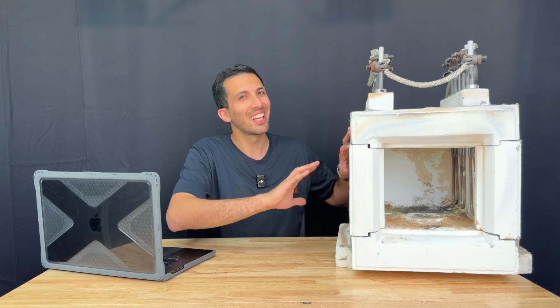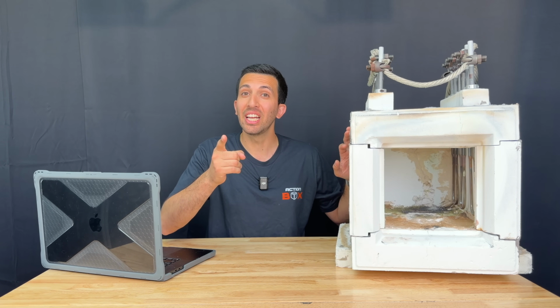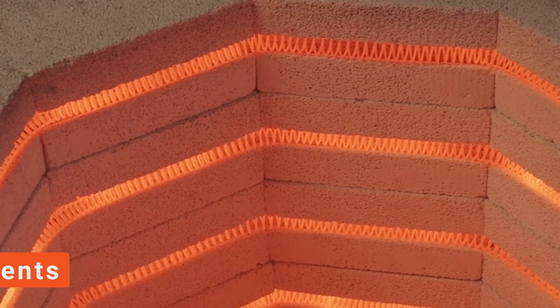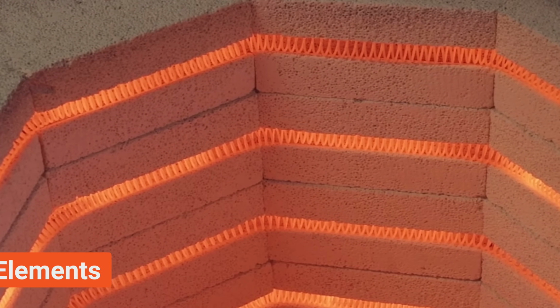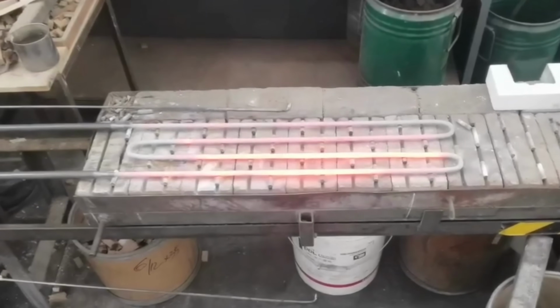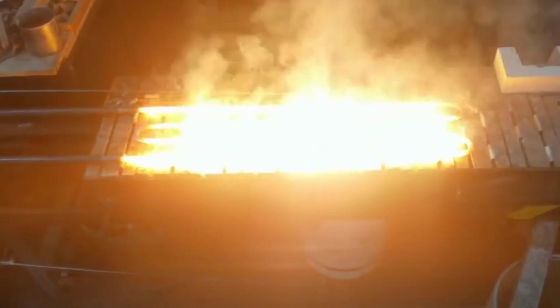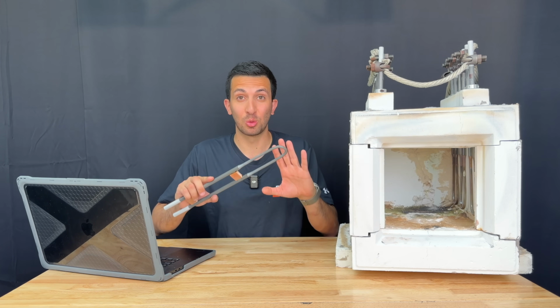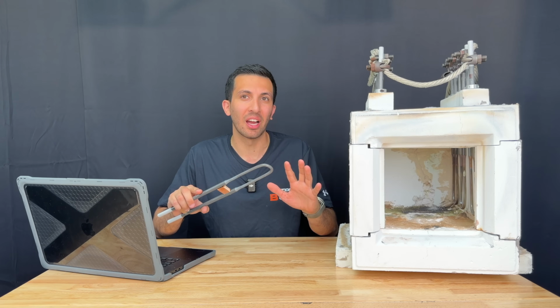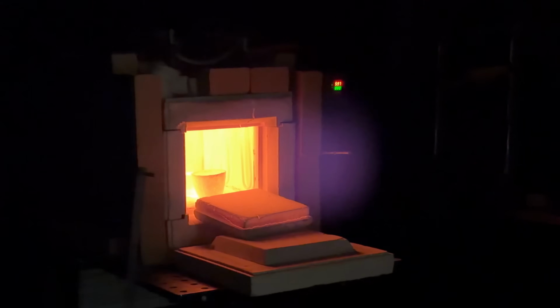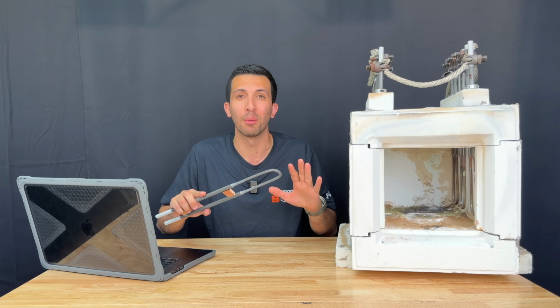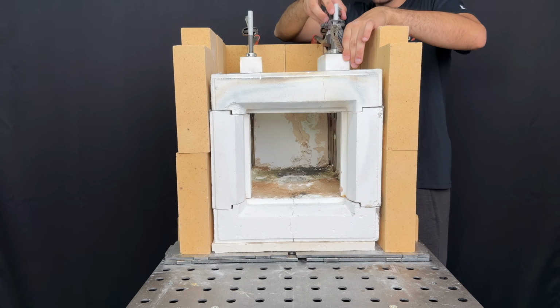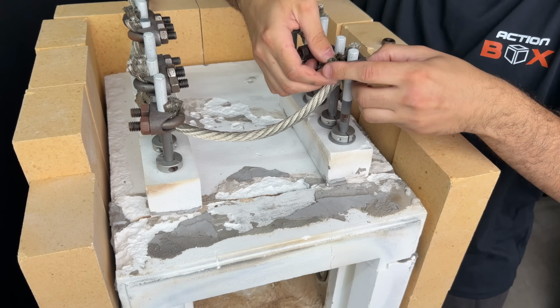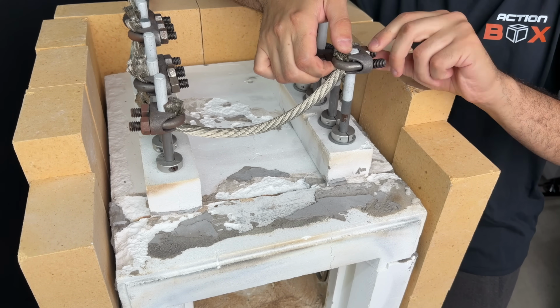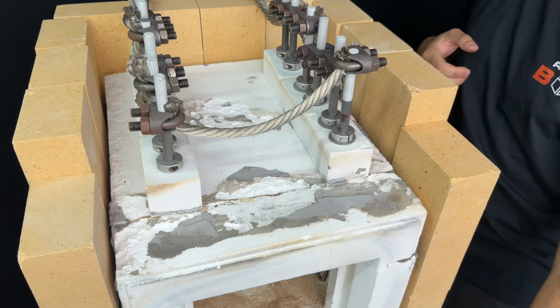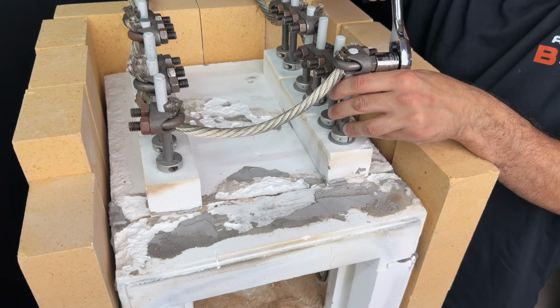Moving on, the furnace can only get as hot as the heating elements, but the heating elements in the common furnace are made of materials like nichrome, which will melt at the temperatures we're going to. So in industry, they use silicon carbide for heating elements in furnaces that go up to 2600 Fahrenheit. But the most impressive heating element, which is what I'm using, is molybdenum disilicide, which is actually a ceramic and is capable of heating up to 3400 Fahrenheit without a problem. These are relatively affordable, so I bought 6 and installed them from the top. I decided to connect them in series using nickel-coated electrical cable to avoid copper oxidation because I anticipate this will get really hot being in direct contact with these heating elements.